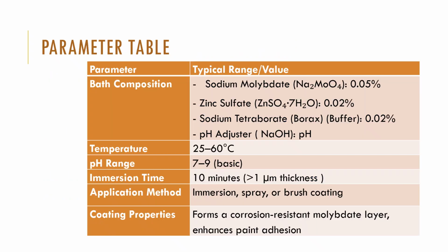Let us see the parameters, that is what is there in the molybdenum bath. Okay, you prepare a molybdenum bath, either you give an immersion coating or you spray on the surface. So what does this bath comprise of? Bath composition: we have sodium molybdate 0.05%, zinc sulfate 0.02%, sodium tetraborate 0.02%, which plays the role of buffer. NaOH is used as a pH adjuster.